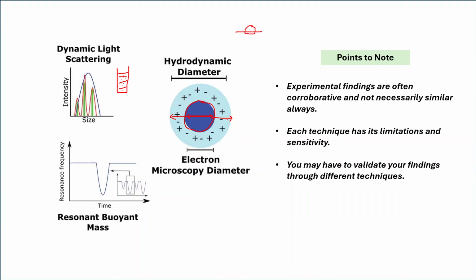But if you're finding your electron microscopy diameter is 50 nanometer, but hydrodynamic diameter is 350 nanometers, that suggests that your nanoparticles are undergoing aggregation in suspension state, which is not good. So that is why different characterization techniques are available to characterize your nanoparticles.